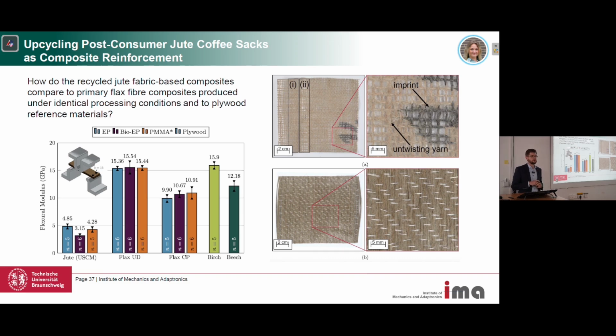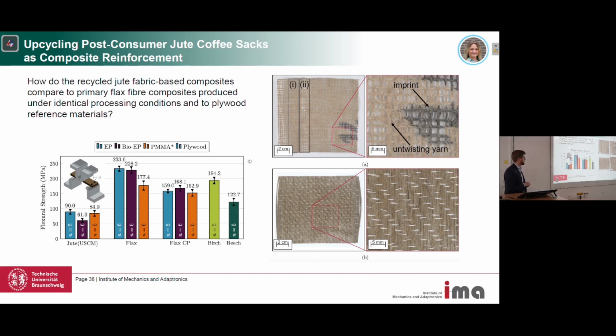So maybe for low load applications, it is possible to use these jute coffee sacks from waste to create new composite materials. And the challenge is, you can see here the primary flax material, which is quite even and homogeneous, and in the coffee sacks you have some defects and imprint, and also untwisted yarns, which impede the mechanical performance. And same goes for the flexural strength, which is also higher than the neat resin, but not so high as the primary natural fiber materials.